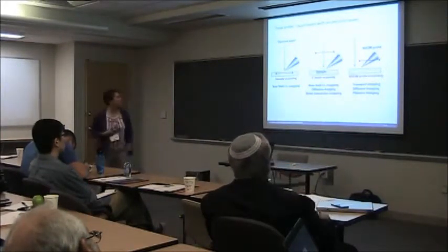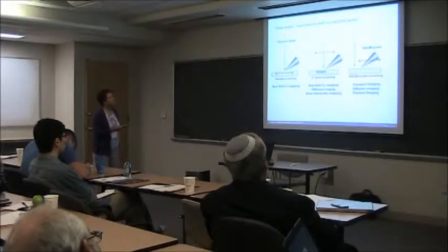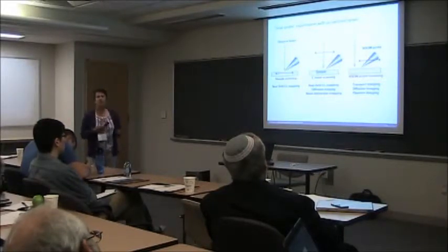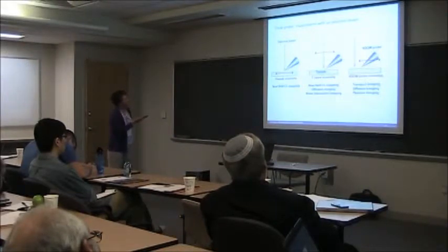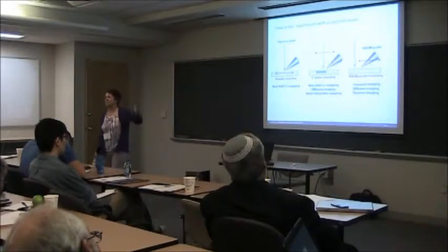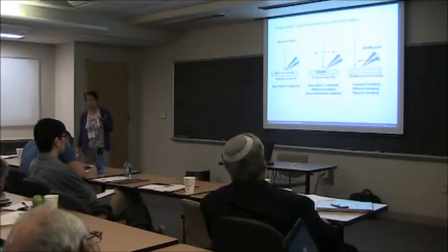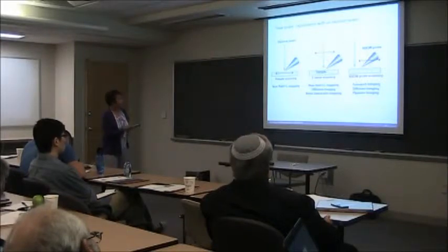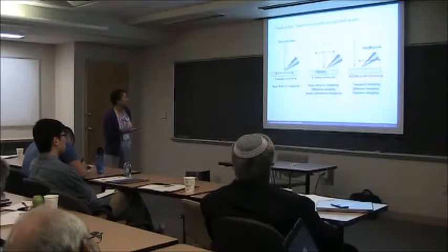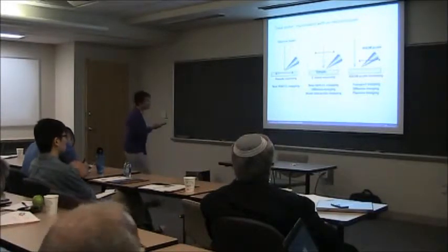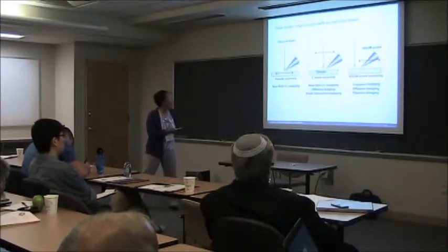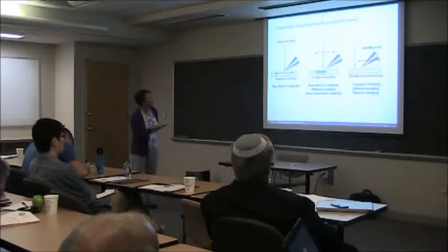So you can do this in a lot of different ways, and actually in the very earliest papers that I found, there are a couple of groups, I'll show you the references here in a minute, that did this. What they were interested in was near field CL. They wanted to do CL mapping, just like the things I showed you earlier, only they wanted higher resolution than you get with traditional CL. And so they designed their system to scan the sample. And we'll talk about that a little bit more, some of the pros and cons and how far you can really push the resolution, but that was with sample scanning.